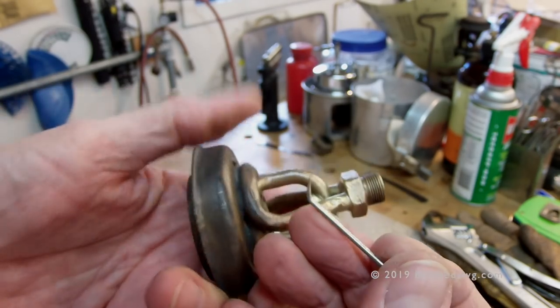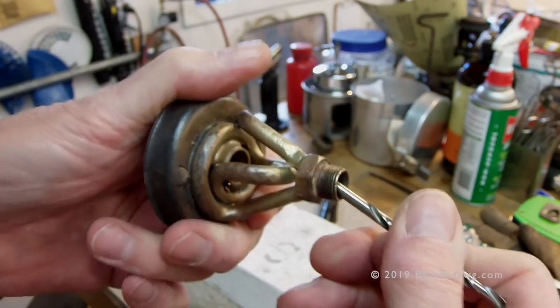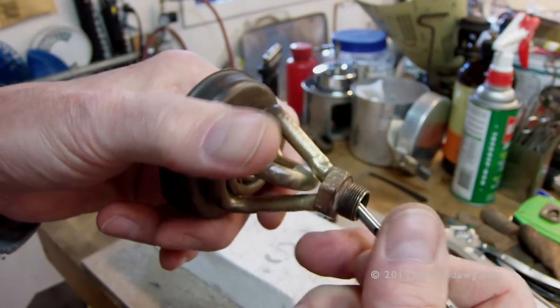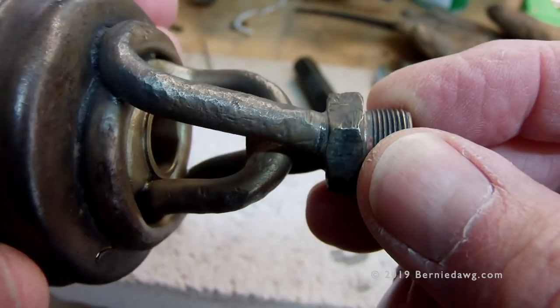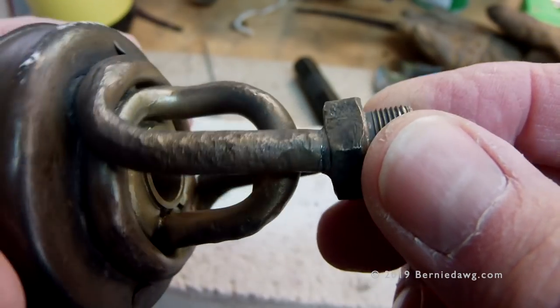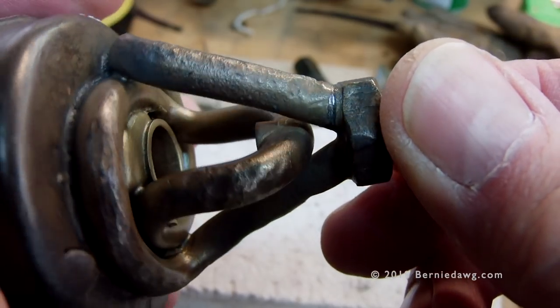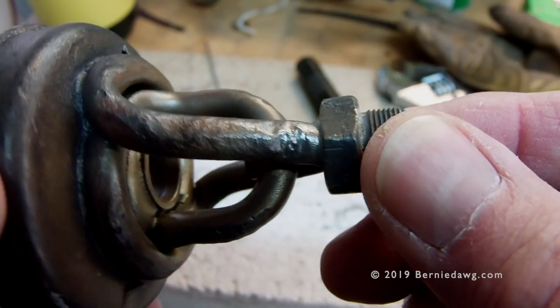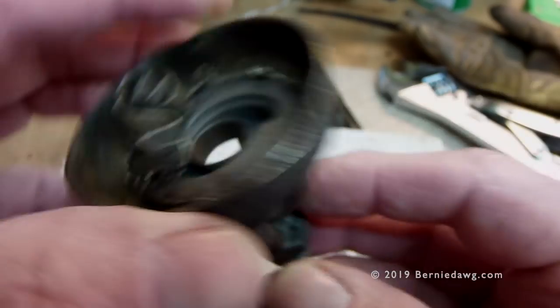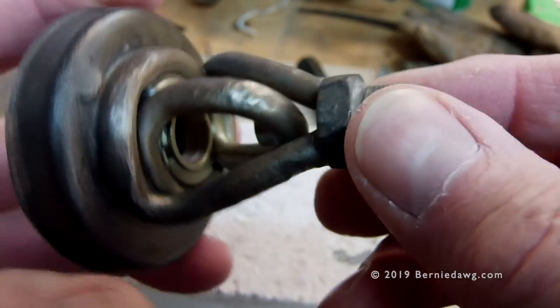I got a drill bit that just fits inside the opening. I have a complete set of machinist numbered bits in different sizes, separated by just a few thousandths. By alternating annealing the tubes and running a new bit in, wiggling and forcing it, I was able to restore a lot of the tubes so they're not so crushed. I've also started removing the perforated ring — I take pliers and wind it up like a sardine can, and it rips along the holes.